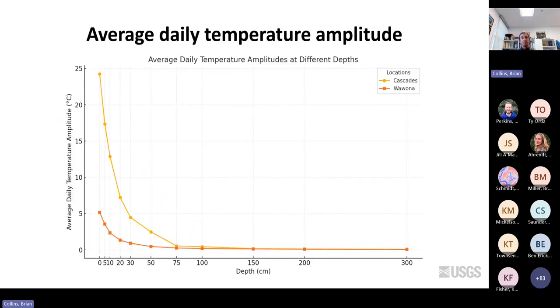When I go back to the results of the borehole measurements, you can see the average daily amplitudes at different depths on this figure. And you can see in the south-facing slope that this amplitude is reaching almost 25 degrees daily on average on the surface, while only 5 degrees in the north-facing slope. And these daily oscillations are visible down to 1 meter, almost every day.